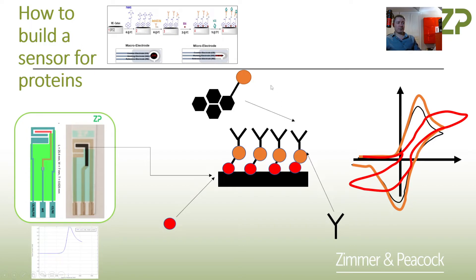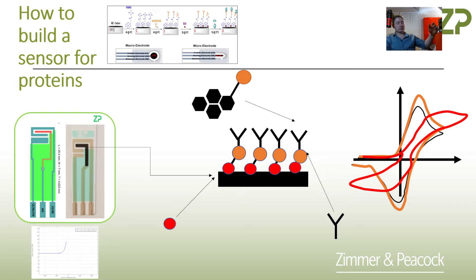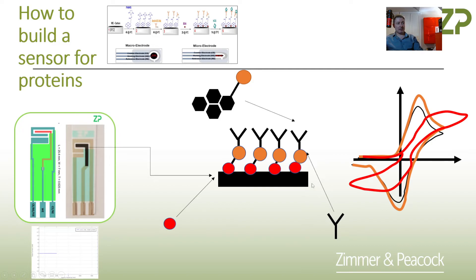The reagent we're using is a pyrene-NHS molecule. It's nice because the pyrene group bonds well to the carbon surface — probably via pi-pi stacking, as both the carbon surface and the pyrene group are rich in pi orbitals. It's already NHS-activated, so you can add the antibody and it will essentially just bind to the surface. You may then want to add a blocking layer, as mentioned in the paper, and we follow each step by quartz crystal microbalance.